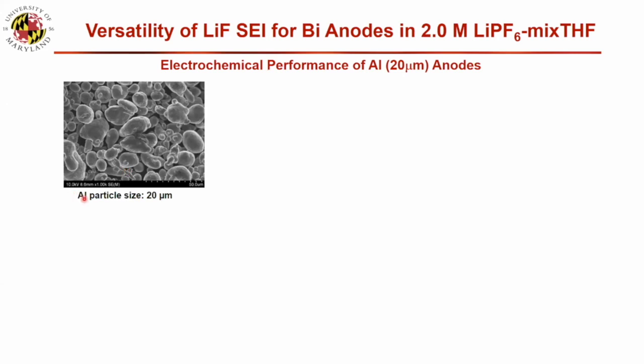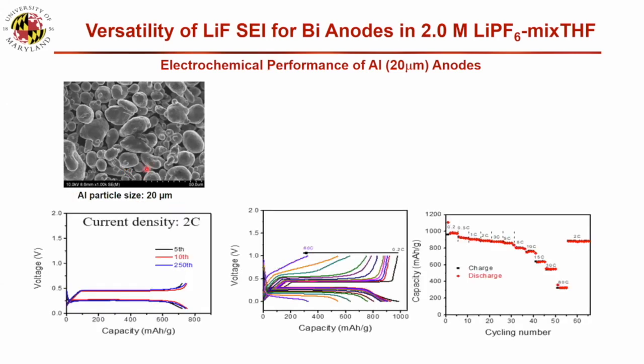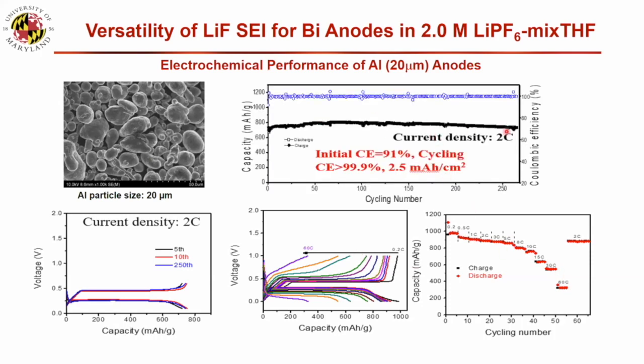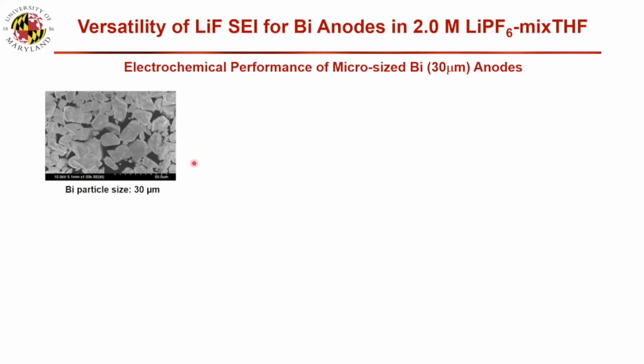So we tested aluminum, 20 micron. And we charge at different rate capacities, and cycle life. So this is 250 cycles, and they are also stable. Micro size, first coulombic efficiency 91 percent, similar to graphite. And not only aluminum, bismuth, same thing, 30 micron, and without any treatment.